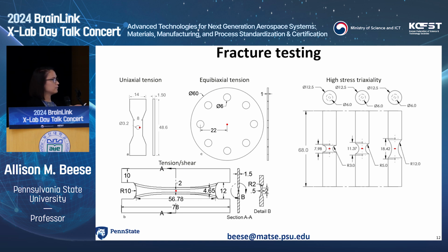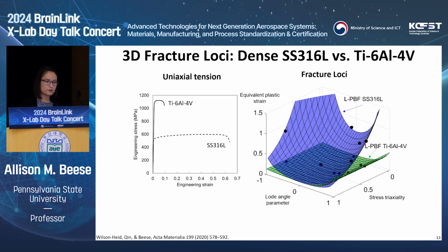This is to think about if we have high stress triaxialities: these are round notch tension specimens, and then combined tension shear. And so what we do is we test our material in all of these different stress states, and we measure the ductility that we get. So basically how much plastic strain we had at that red point up until failure. And that allows us to get those fracture loci that I said we were interested in at the beginning.